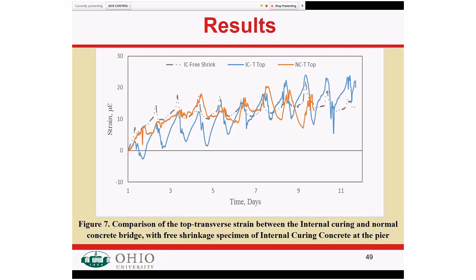All right, we did put a free shrinkage prism next to the deck just to see how that would compare. And again, the gray line here is the free shrinkage prism. The orange line is the strain gauge in the deck, and the blue line is internal curing near the top of the deck. And again, you can see that the strains are generally lower in the internal curing, and even lower than in the free shrinkage sample. And that's to be expected.